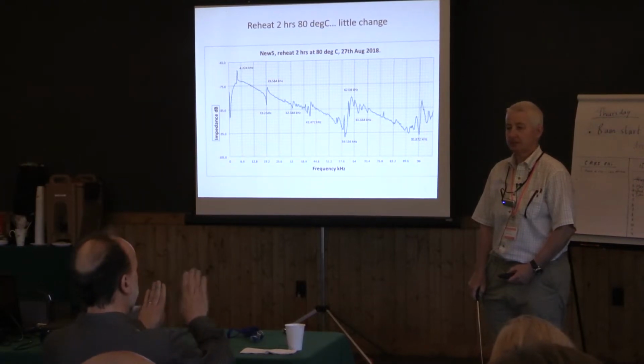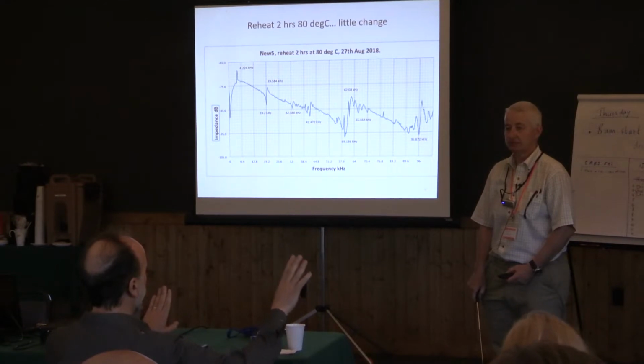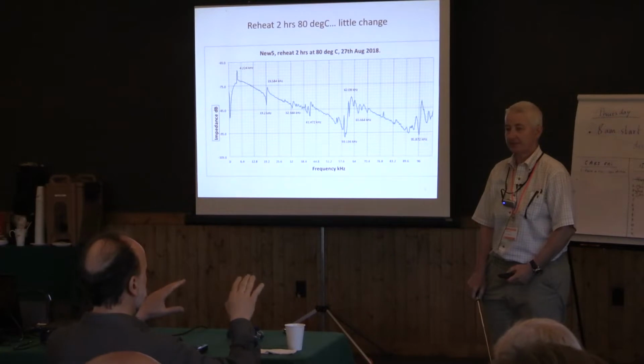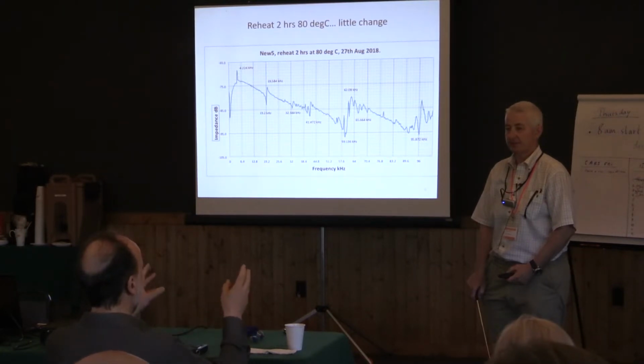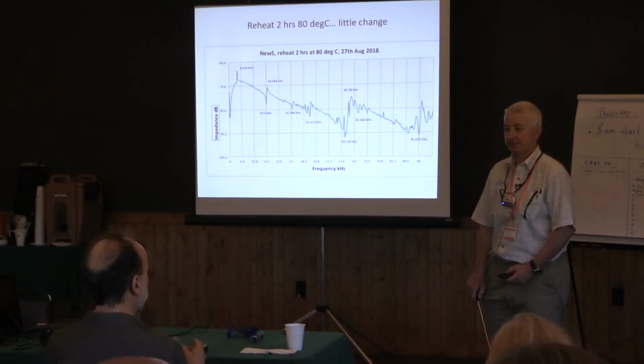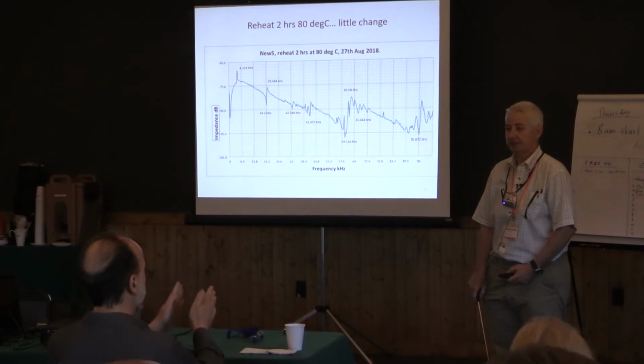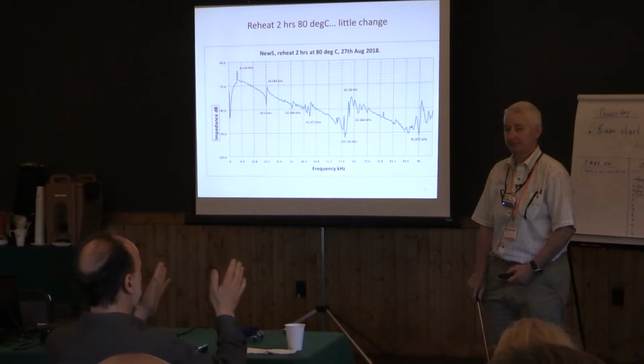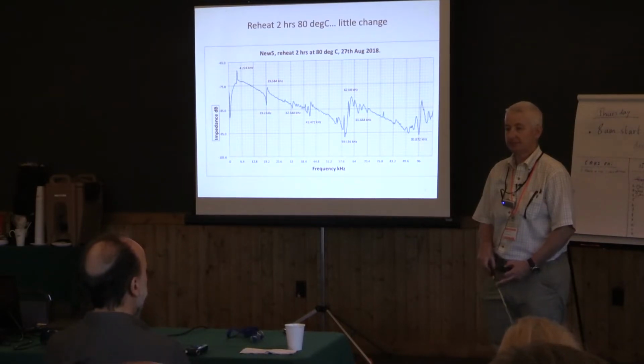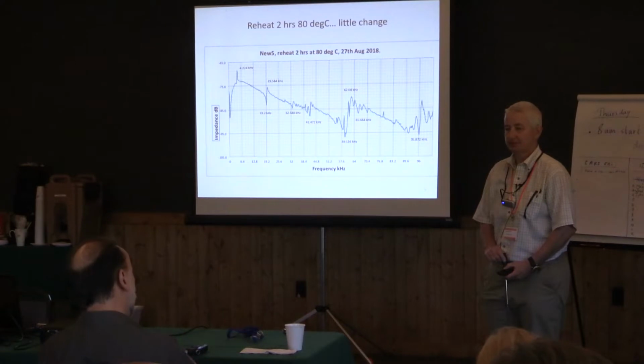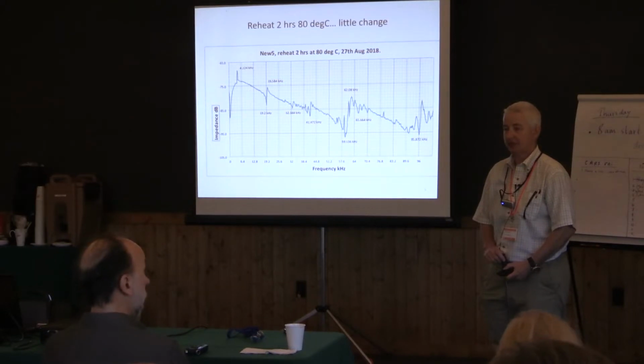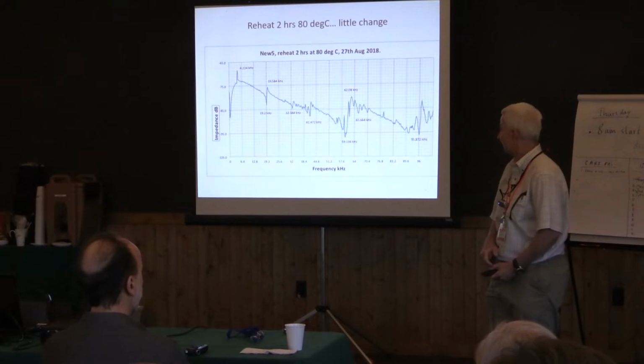The issue is again whether you want to have the optimal cure for the epoxy such that it has the highest glass transition temperature, or you want to take into account the fact that it will contract as you go from the glass transition temperature to room temperature and will produce residual stresses if it is glued, for example, to this PZT. So the higher the temperature at which you cure it, the higher the residual stresses are going to be. As you go to higher temperature, you're going to have a material that has higher temperature resistance, but on the other hand, you're going to have more residual stresses, which means that the material is going to be more prone to cracking because it's going to be closer to the threshold at which you crack. Therefore, the question of an optimal cure is not something you can get from...